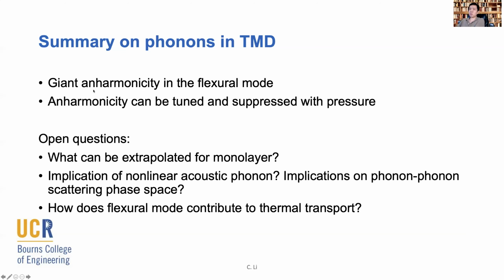And so in summary, we see a very large anharmonicity in the flexure mode that involves the out-of-plane atomic vibrations. And we can easily tune that with pressure. And we actually can observe some transition into more covalent-like bonding well below the phase transition. So that actually is interesting. So the phase transition might not be directly driven by this covalent bonding, at least not in the same pressure region we were talking about.